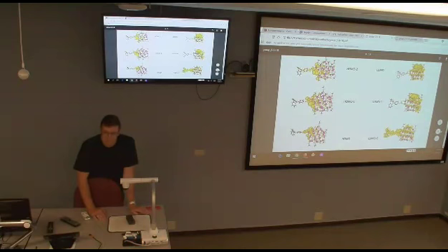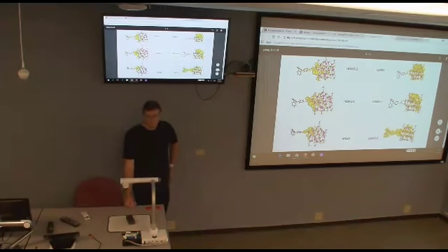So you excite the quantum dot, and then for the hole transfer, it will naturally end up at the LUMO, where it still has a lot of hybridized character. Which means you can probably easily get to states whose couplings with other states coming from the quantum dot would be strong, because you have a lot of contribution from the quantum dot. But on the other hand, the recombination is also enhanced. If your electron is still in the system, it might recombine non-radiatively, and you lose your excitation. So it looks like it has both a positive and a negative effect.